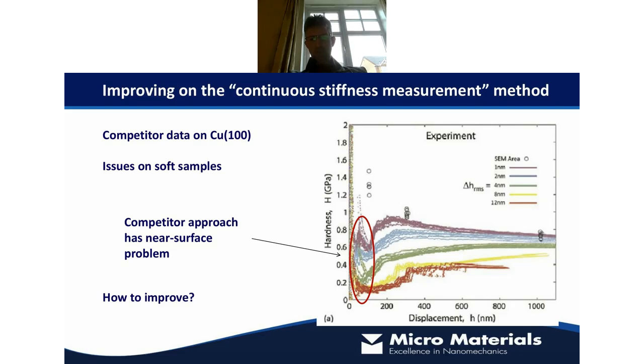So what we can see here are indentations on copper 100, and the SEM area measurements with this competitor system. So this is the true hardness. As Stefan was saying earlier, you can measure the contact area accurately through an SEM and apply one of the corrections that Stefan's talking about, and that allows you to get the true measurements. It's a little bit worrying. There's a scatter there, but nevertheless.